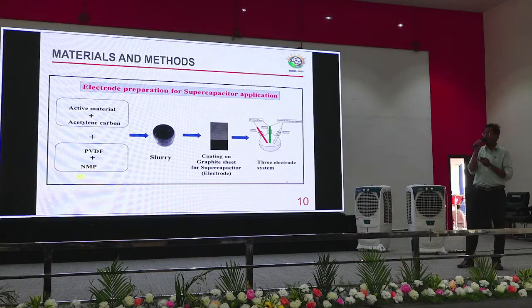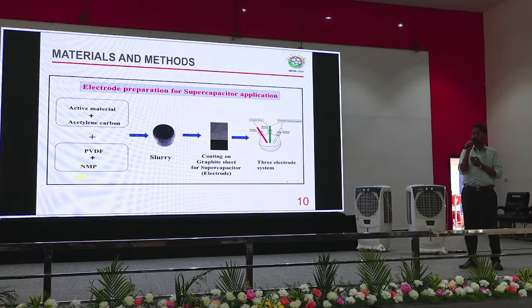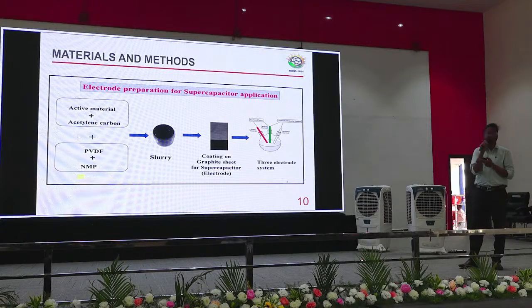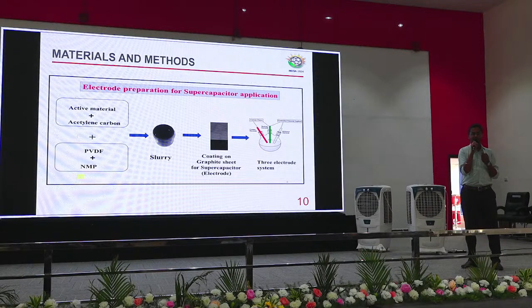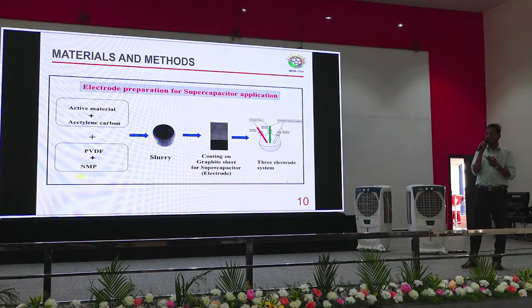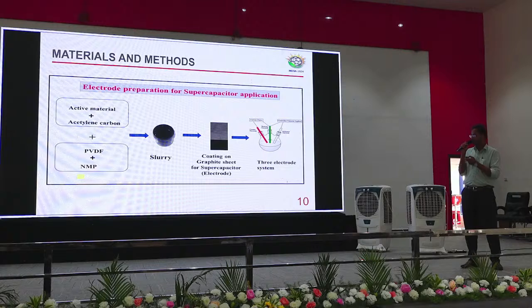Already we know the electrode preparation for supercapacitor application. First we take the active material, acetylene carbon, PVDF and NMP to make a slurry, and coat it on the graphite sheet I am using here. People use nickel foam also, which involves a lot of procedure, like etching. But here I directly take the graphite carbon, clean it with ethanol, and use it for the slurry preparation to make the electrode for the 3 electrode setup, and then move on to the 2 electrode, making a coin cell device.